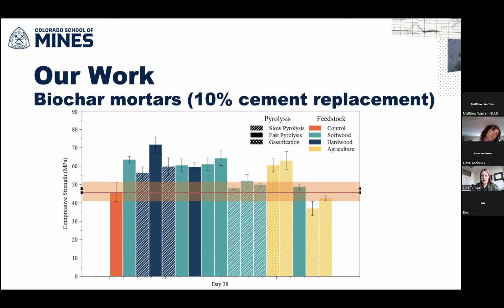So as I mentioned, our group has had a lot of success with biochar, and that's a little bit in contrast to a lot of the literature out there. Most folks see strength decreases with replacements above, say, 2 to 5% of the cement with biochar. In contrast, we're seeing strength improvements upwards of cement replacements of 15%. This plot here is showing cement replacements with 10% biochar.